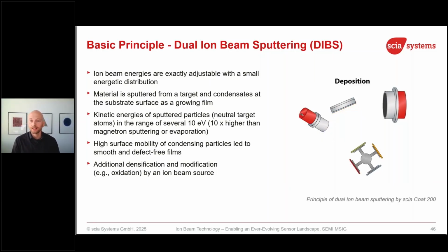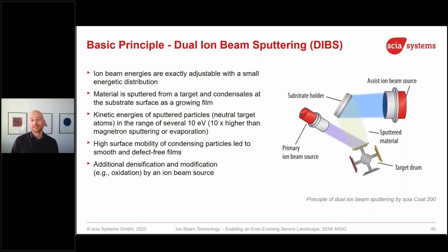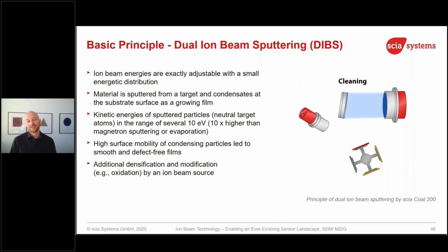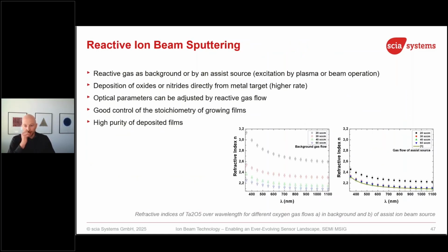What is the advantage of ion beam sputtering compared to magnetron sputtering? It's much more precise, it's very uniform, you get high density layer, you can control the properties nicely. Disadvantage, it's much slower, maybe 5 to 10 times slower compared to magnetron sputtering. Anyway, there's one big advantage. We can control the stoichiometry of certain layers very precisely.